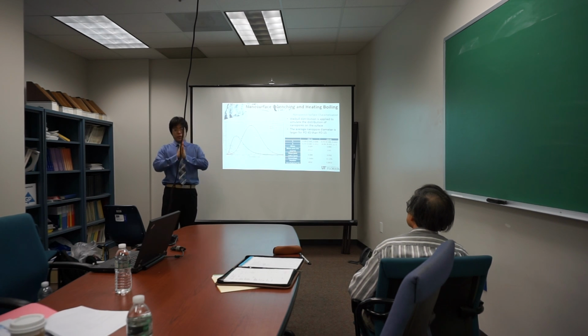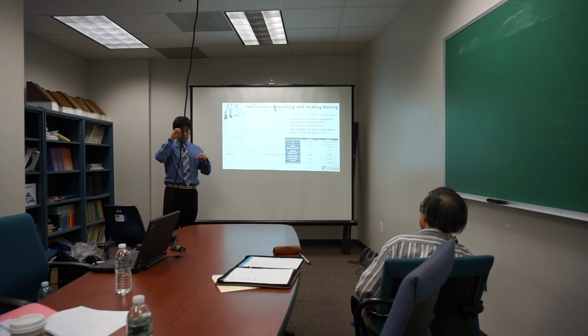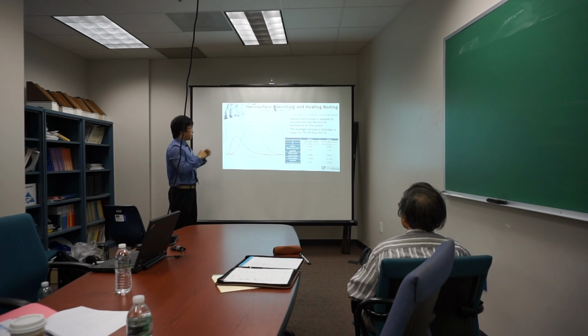So I take SEM pictures at 3 different locations, and then I use MATLAB to take the picture and try to find its boundary. When I find the boundary, the black ones refer to the holes, and the lighter ones, like the gray, refer to the surface. Then I can catch each of the holes, the size of the holes, and put them together to create a histogram.